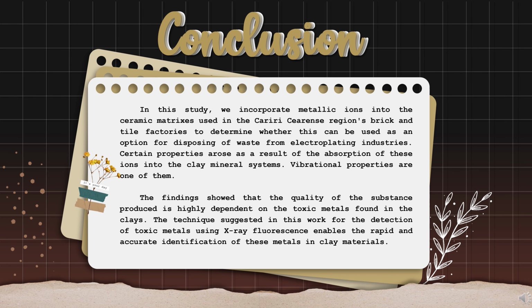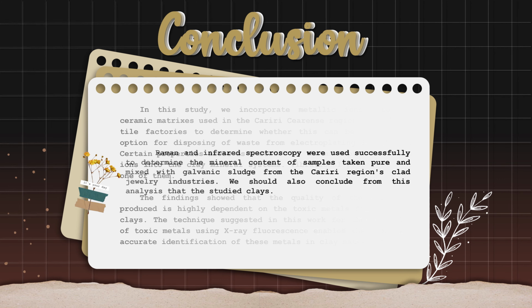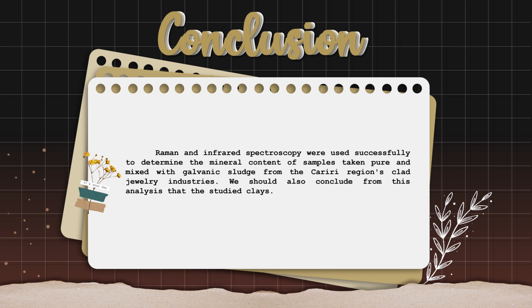The method for X-ray fluorescence identification of toxic metals proposed in this paper allows for the fast and accurate detection of these metals in clay minerals. The mineral composition of samples taken from Cariri region's clad jewelry industries, both pure and mixed with galvanic sludge, was successfully determined using Raman and infrared spectroscopy. With this result, the researchers concluded that the clays that were tested can be used as toxic metal absorbents, eliminating the toxic metals from solutions or water from industries.